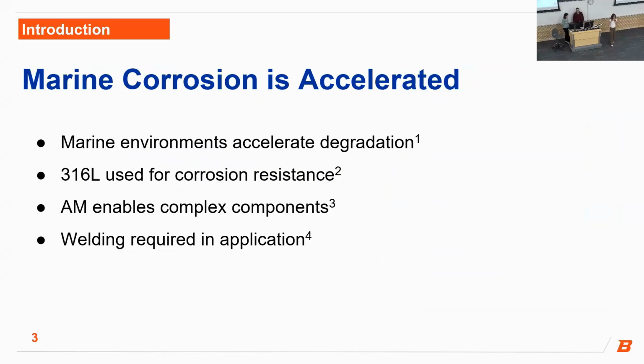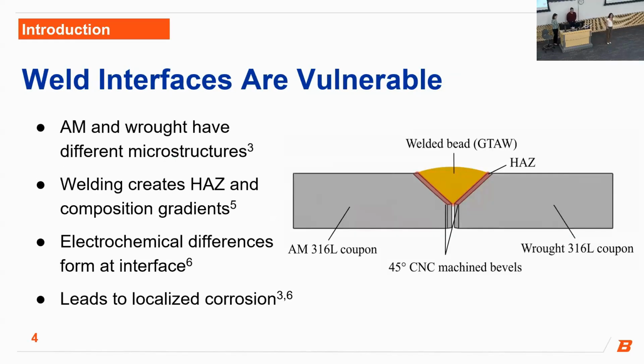Corrosion is a major issue in naval environments where materials degrade more quickly. 316L stainless steel is commonly used for its good corrosion resistance, and additively manufactured or 3D printed stainless steel can be used to make more complex geometries. However, welding is required to join the two in application, and when you combine these conditions, it can cause issues at the interface. Although additively manufactured and wrought stainless steel are the same compositionally, they have different microstructures. Welding introduces a HAZ, or heat affected zone, which is highlighted in red on our diagram, as well as compositional gradients. This can lead to electrochemical imbalances at the interface, which can drive corrosion.